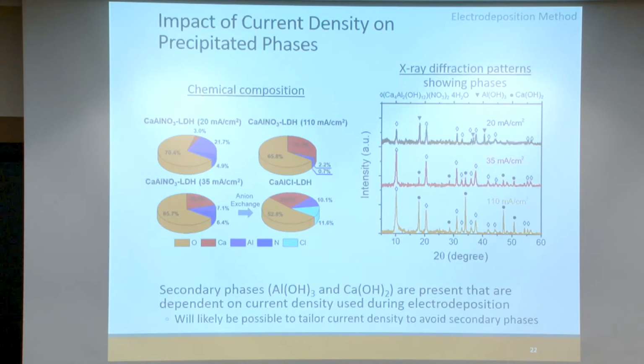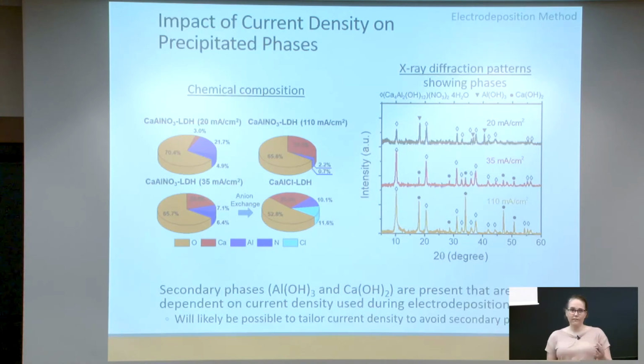Now, by playing around with the current density that's applied during electro-deposition, we can change what phases are present. And so in addition to the layered double hydroxide that forms, we have been getting secondary phases that form. And this can be explained by what I was discussing previously in terms of the impact of pH and the relative ratios of the different cations. And so what we see here is for a low current density, we end up with a layered double hydroxide, which are the diamonds, and then the secondary phase is aluminium hydroxide, which is the upside down triangles.